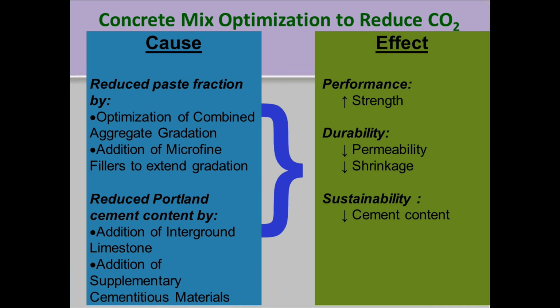In the mix design, we can optimize aggregate gradations. We can extend that with microfine fillers. We can use interground limestone. We can use SCMs. And we can make concrete that has reduced permeability, reduced shrinkage. We can reduce the cement clinker content of the concrete and still get up to strength. And